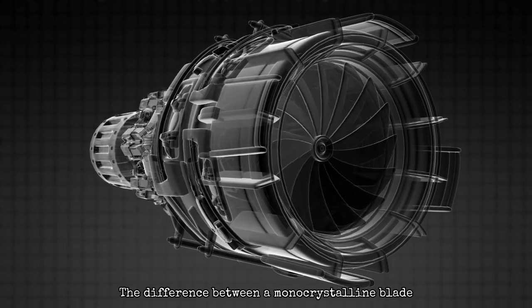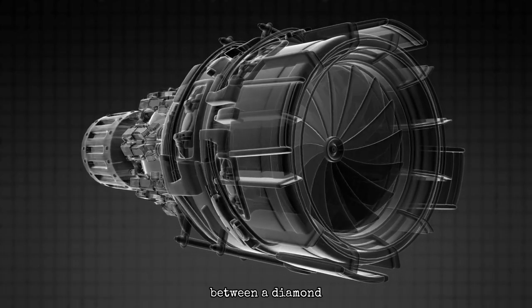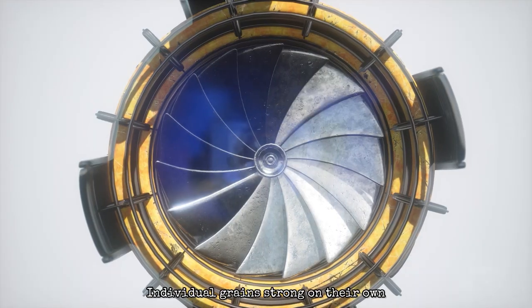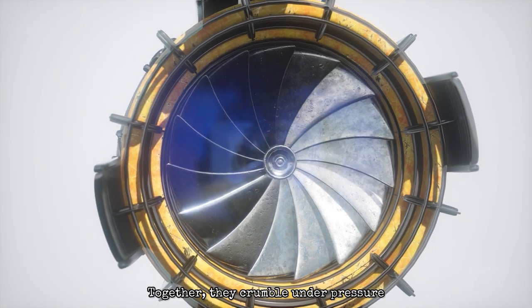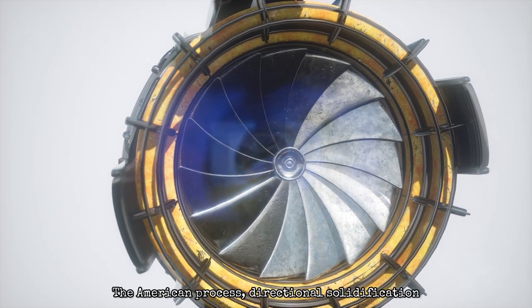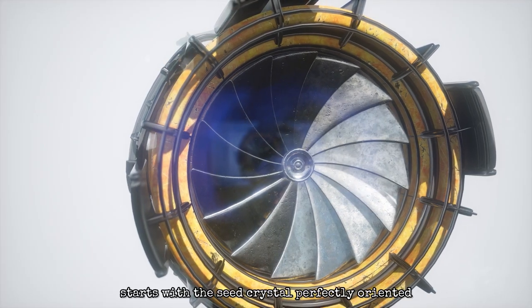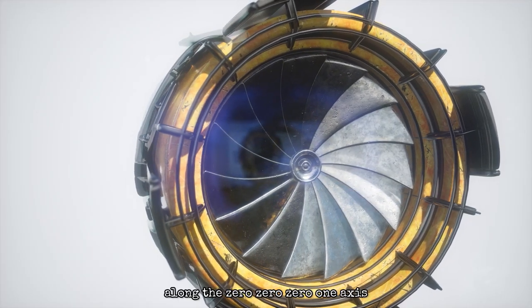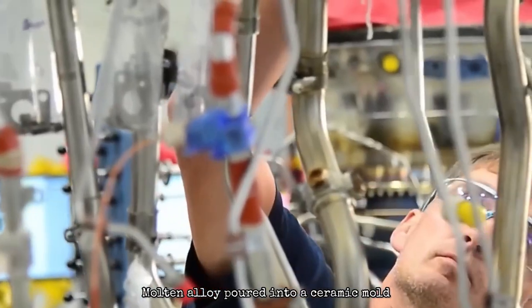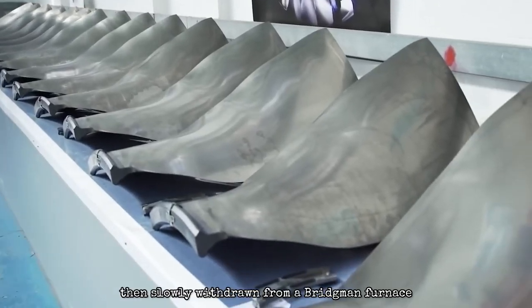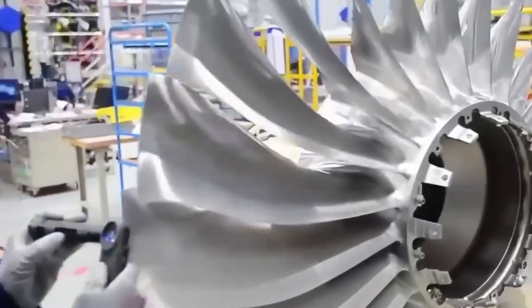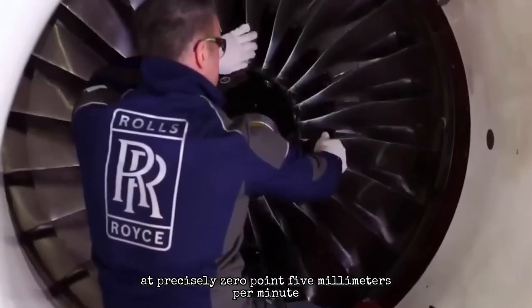The difference between a monocrystalline blade and a polycrystalline one is the difference between a diamond and a bag of sand. Individual grains strong on their own. Together, they crumble under pressure. The American process, directional solidification, starts with the seed crystal perfectly oriented along the 0001 axis. Molten alloy poured into a ceramic mold, then slowly withdrawn from a Bridgman furnace at precisely 0.5 millimeters per minute.